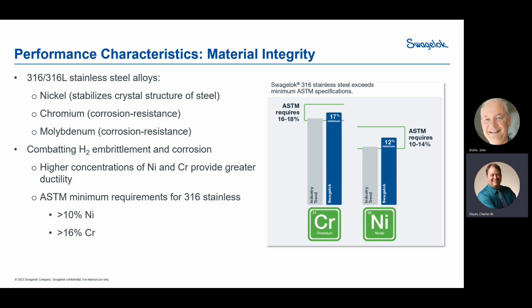We also find that it's important to reach chrome level from 16 to 17%. That chrome and our moly all help with corrosion resistance. So corrosion pitting can cause cracking and hydrogen to be able to enter the material. So corrosion is something we want to watch out for. So combating hydrogen embrittlement, combating corrosion comes down to these two primary points inside your material characteristics, this nickel and chrome.